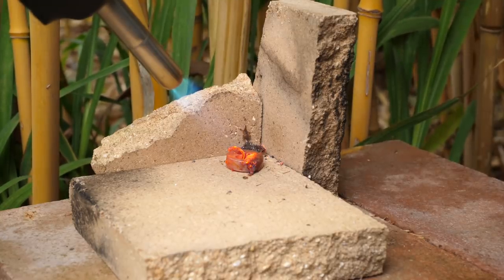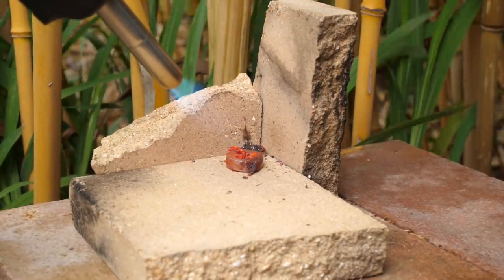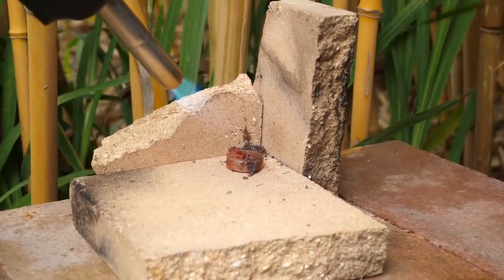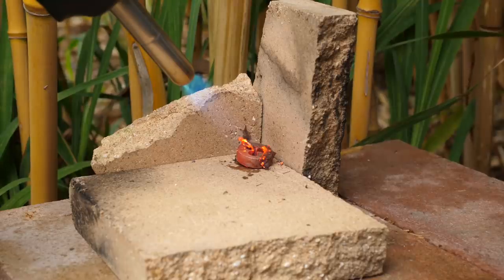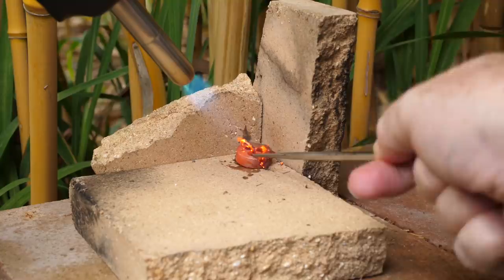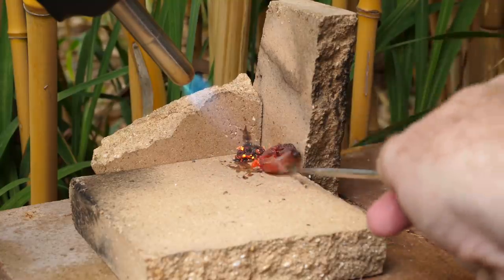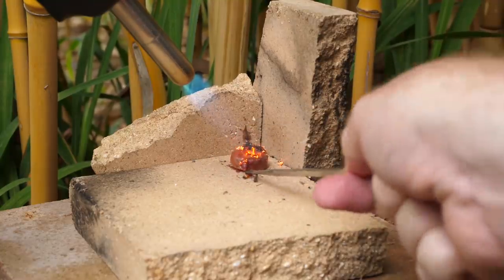Silver steel needs to soak for a short while after reaching the right temperature to make sure it's heated through. With the wind gusting it was tricky to find a moment when all the parts of the die were heated to red fairly evenly, but eventually I got the right moment and quenched it.